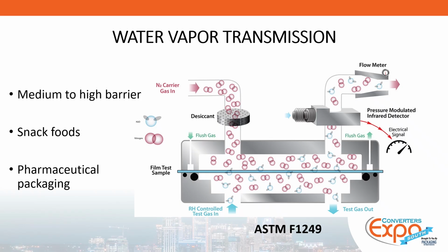So ASTM F1249, this is a schematic of a diffusion cell where you have your barrier film in the middle, and in one chamber we have controlled RH, and in the other chamber we have dry nitrogen. As the moisture passes through the film, the dry nitrogen sweep takes it past the pressure modulated infrared detector, which is converted into grams of moisture through your barrier material. And this is a very robust method that is more sensitive than the E96 method, and it's also more repeatable due to the sensitivity that we get from the pressure modulation of the infrared detector.